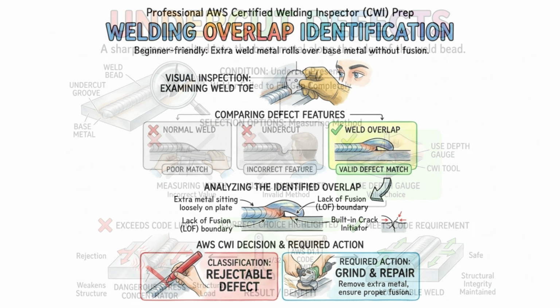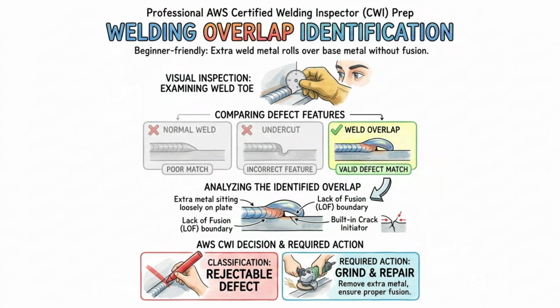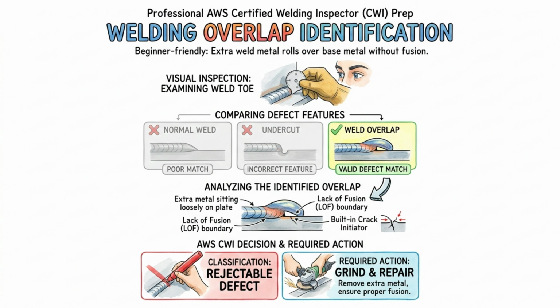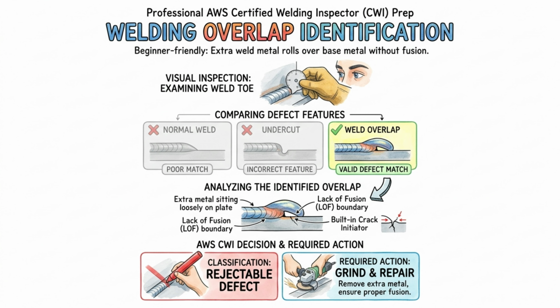Another frequent visual defect is overlap, which happens when the weld metal rolls over the edge of the base metal without actually fusing to it. Unlike undercut, which is a groove, overlap is extra metal sitting loosely on top of the plate like a small shelf. This defect is easily caused by incorrect travel speed or poor torch angle, and it creates a built-in crack initiator that will fail under stress. Whenever you spot overlap during an inspection, it is automatically classified as a rejectable defect that requires grinding and repair.